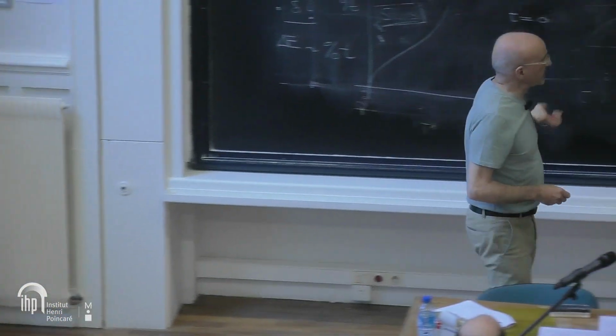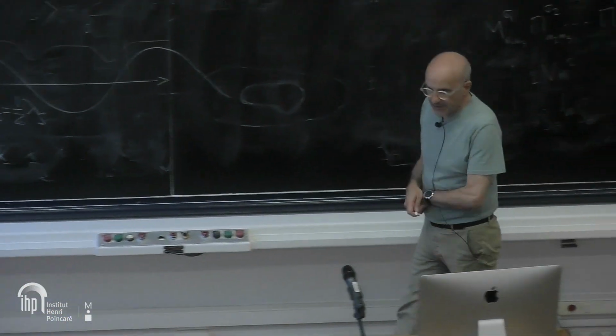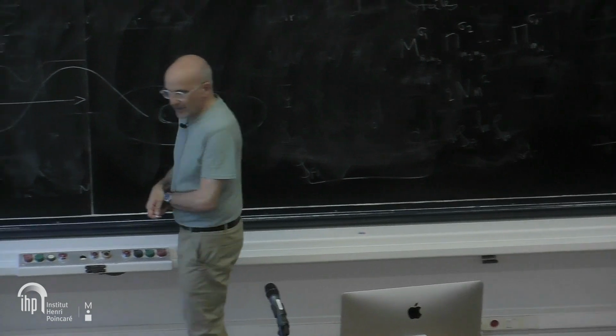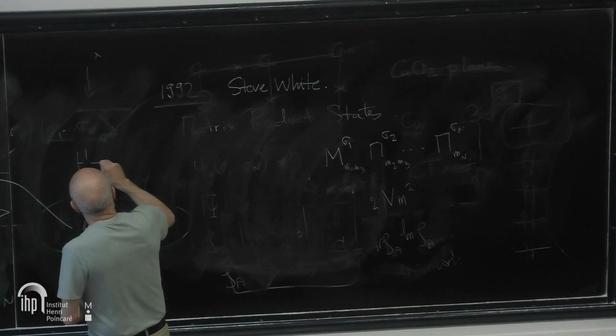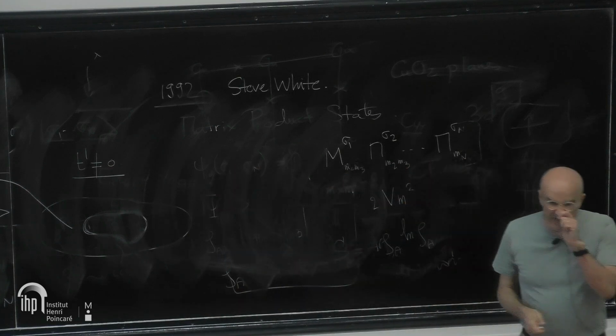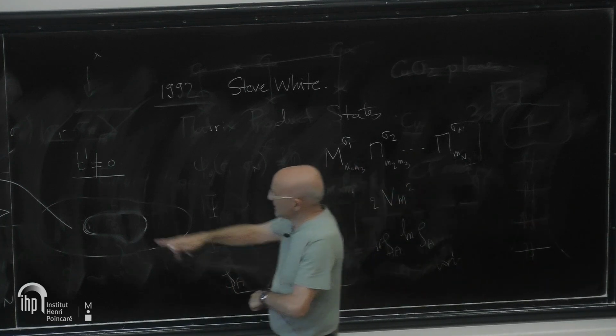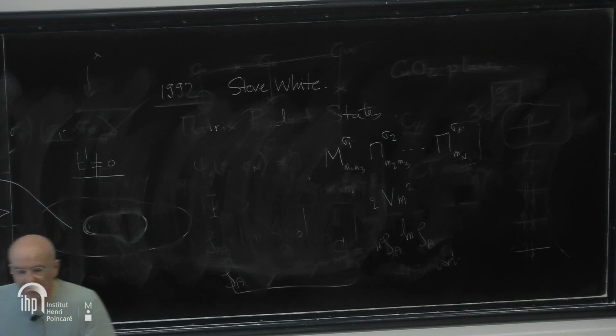Now, does that mean that the Hubbard model does not sustain superconductivity in the ground state? Well, the answer is no. When t' is different from 0, it has been recently established in the past couple of years that this energy balance becomes favorable to d-wave superconductivity, which eventually wins over stripe ordering. The ground state can sustain both charge density wave and superconductivity together, but there is a non-zero d-wave order parameter.